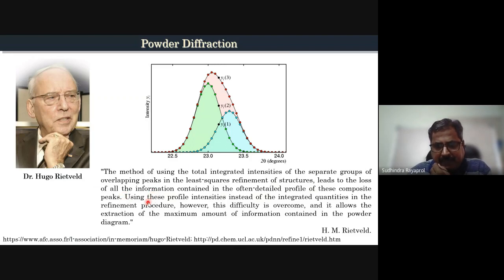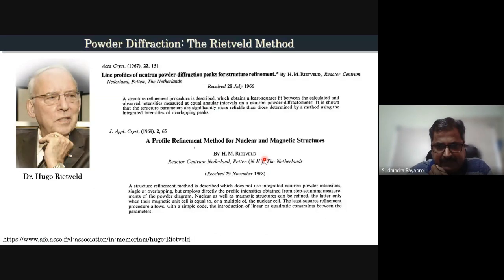Therefore, he came up with a procedure in which these individual peaks could be identified from their atomic scattering, and you can actually get the intensity and position of these peaks to carry out a full profile refinement, instead of relying on single overlapping peaks, and get precise information about the composition of the sample as well as the position and unit cell parameters of that.